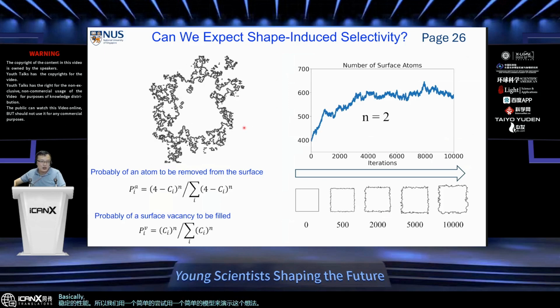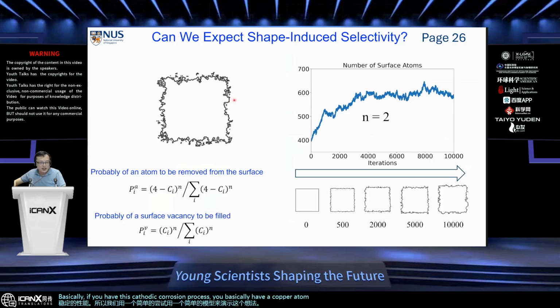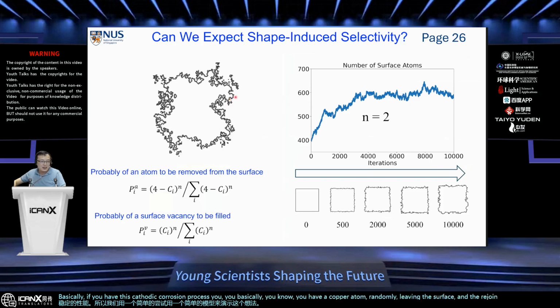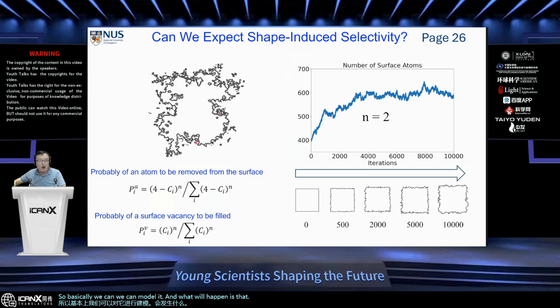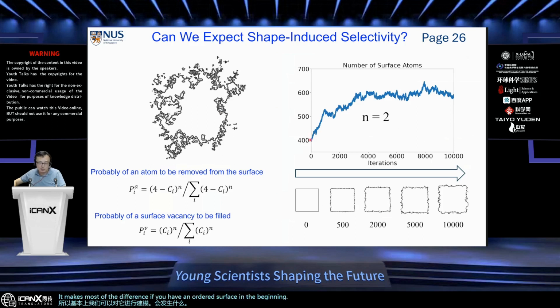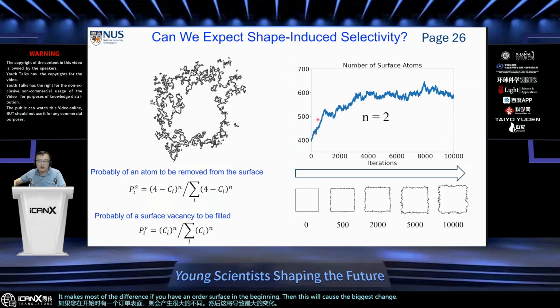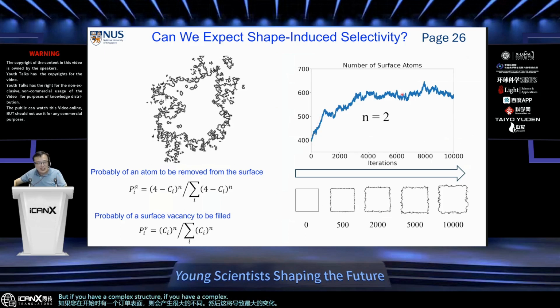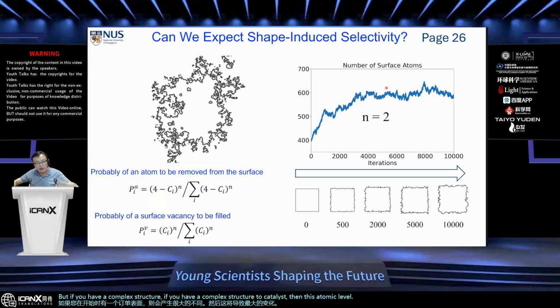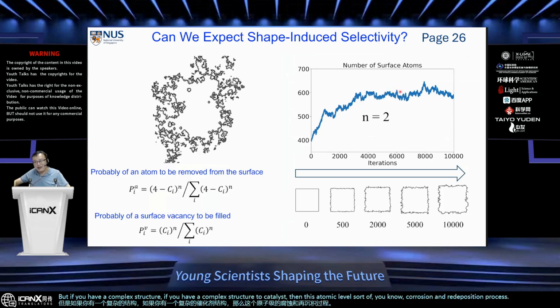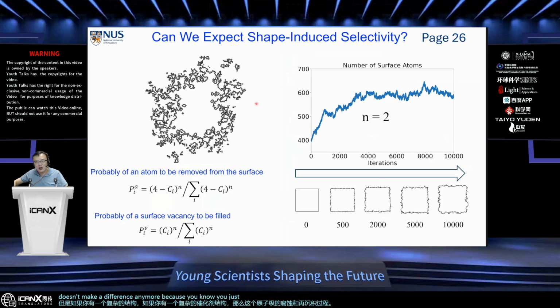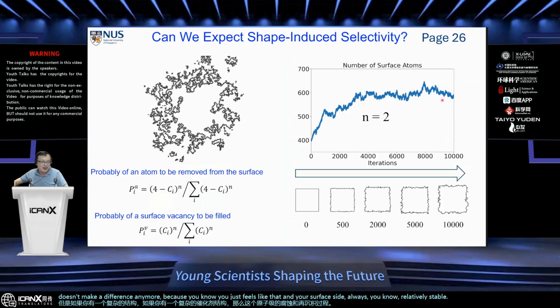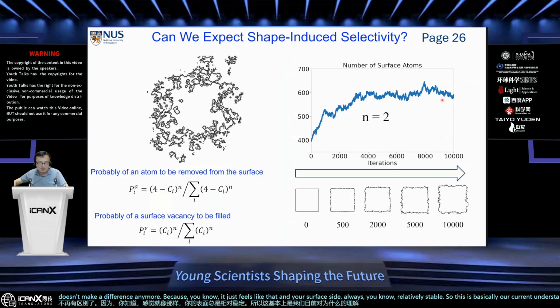Basically, if you have this cathodic corrosion process, you have a copper atom randomly leaving the surface and rejoining the surface. We can model this, and what will happen is that it makes the most difference if you have an ordered surface in the beginning. Then this will cause the biggest change. But if you have a complex structured catalyst, then this atomic level corrosion and redeposition process doesn't make a difference anymore, because it just fills in, and your surface side is always relatively stable. So this is basically our current understanding of the literature data using our theory.